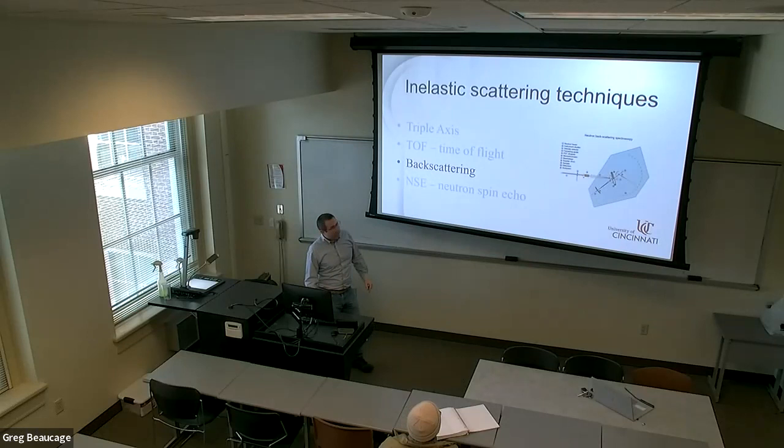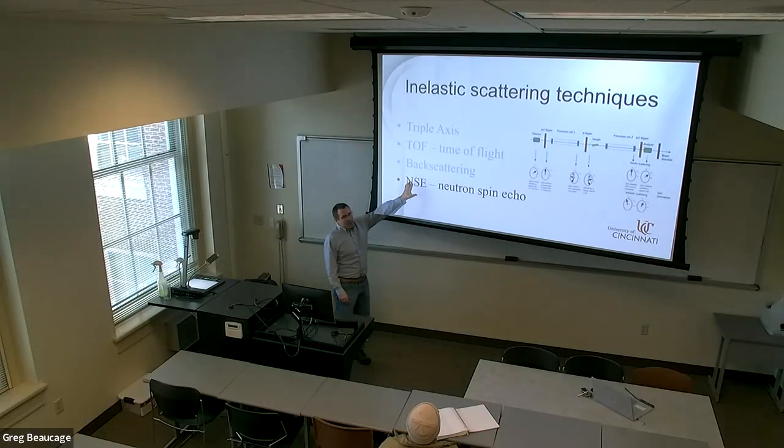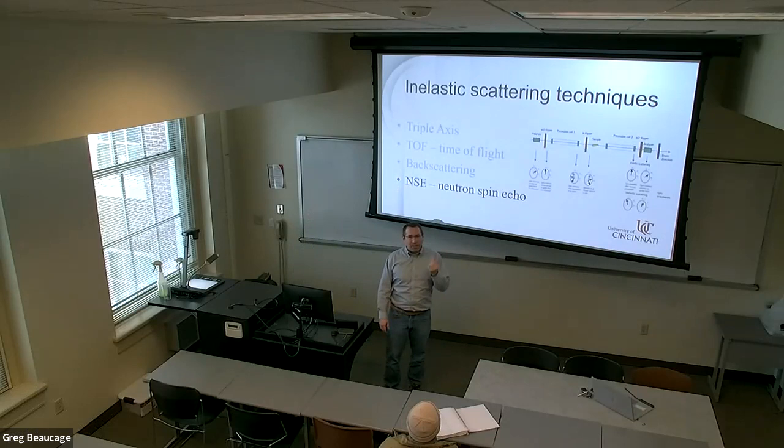All right. And then in polymer dynamics, neutron spin echo has this special place because it can measure slow dynamics, polymer chain dynamics. Slow dynamics are characterized by small changes in the neutron velocity, changes that are too fast for us to mechanically clock or to distinguish the time it takes for the incident beam to hit and a scattered beam to hit. That time is too fast. We can't catch it. So how do you figure out the change in velocity when it's too fast to mechanically clock?